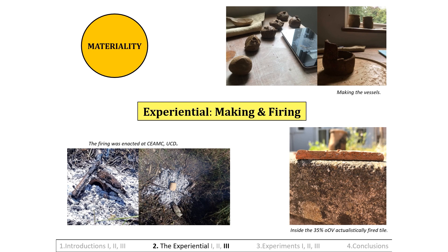Stage 5: Actualistically firing the vessels. The vessels were fired as actualistically as possible to simulate ancient technologies, while ancient craftsmanship is simulated and considered through real first-hand practice of working with gabbroic clay. I have never worked with such a frustrating clay, leading me to believe that it was probably not chosen for its workability. Its apparent lack of plasticity may shed light as to why there are so many gabbroic admixture vessels. As gabbroic clay, especially when inclusions are added, is difficult to work with, it is not surprising that Trevisker ware vessels often appear to have been repurposed, with diverse uses and functions before deposition.